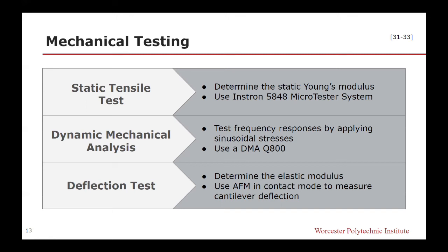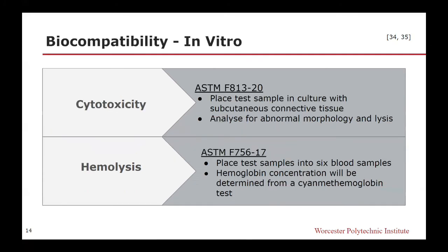A force indentation curve will be produced, and the elastic modulus of the sample can be determined and compared to the known modulus of 111 kilopascals. We'll also be testing the biocompatibility of the device.